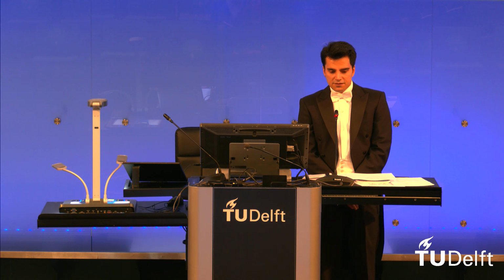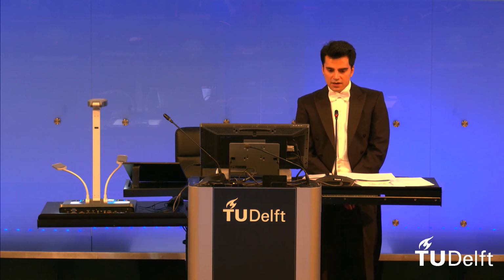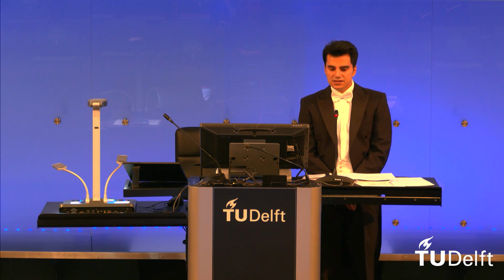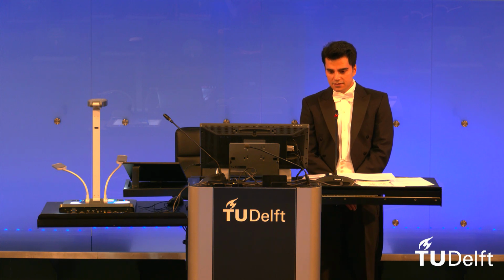So in this sense, if you have a very high chance of sliding, then a higher yield stress wouldn't be beneficial. And referring to your second question, we can say that on a track where you have less chance of high creepage or a high amount of slip, the higher steel grade will be more beneficial. But in case you have a high creepage condition and you expect it in the operational conditions of the trains, then a lower steel grade would be better.